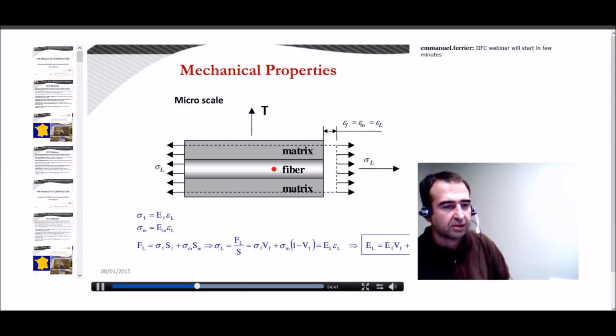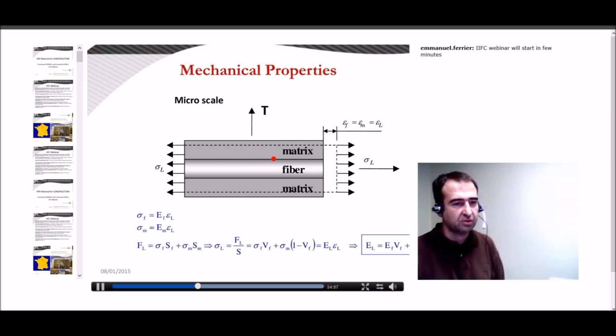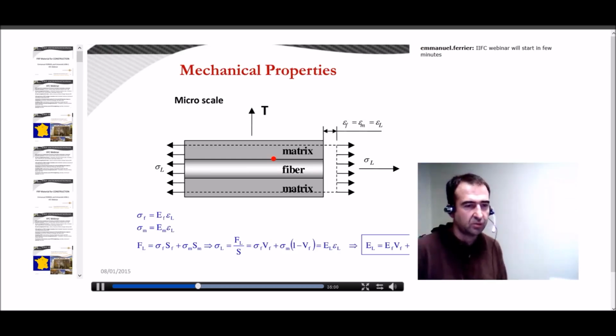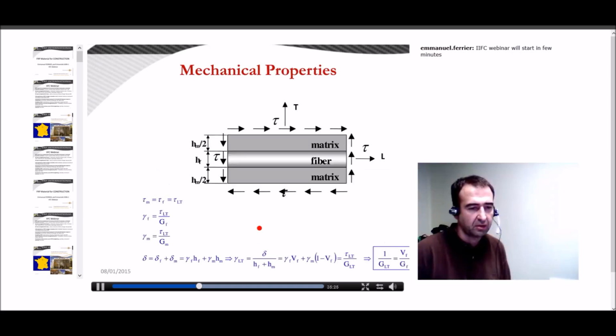So then when we have this, generally we identify the mechanical properties of this using perfect bonding between the fibers and the matrix. This is not often the case, so there is some problem in certain cases between matrix and fibers, and this is well known and well identified. Then it's quite common now to give a very specific treatment to the fibers so that there is a very perfect bonding between these two, so that it allows you to determine mechanical properties considering usual elastic properties of all the constituents.